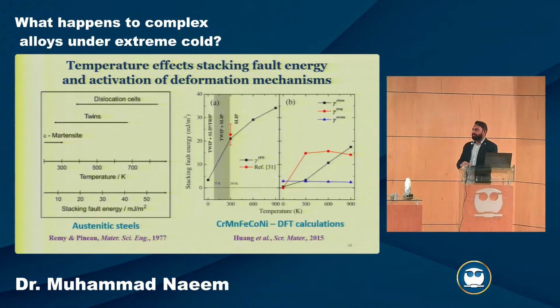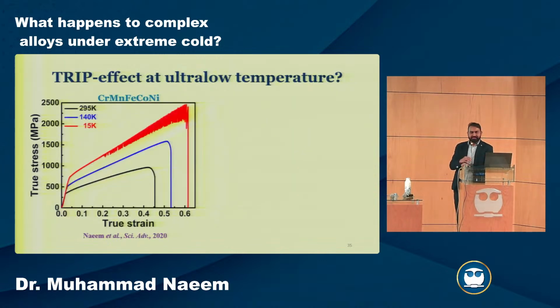When this paper was published in 2014, which I showed in the previous slide, at cryogenic temperature they had twinning activated at 77 Kelvin. Then there was a paper coming from, I think, KTH in Sweden, where they did some calculation and predicted that if you go to further low temperature, below liquid nitrogen, below 77 Kelvin, you would have phase transformation as well, in addition to twinning. So we wanted to see what happened.